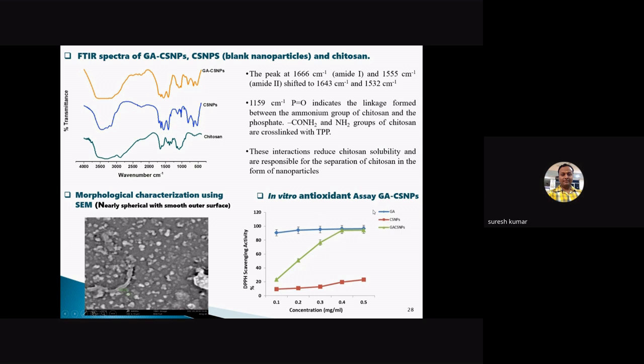Generally, gallic acid is a natural plant polyphenol with high antioxidant activity and shows excellent scavenging property, even when we use a concentration of 0.05 mg per ml. In the case of the gallic acid incorporated final nanocomposite material, the highest scavenging activity was found to be 92.85 at 0.5 mg per ml. It was observed that DPPH radical activity linearly depends on the percentage of encapsulation of gallic acid in the total